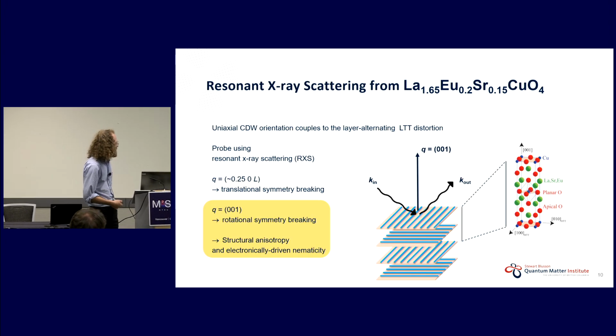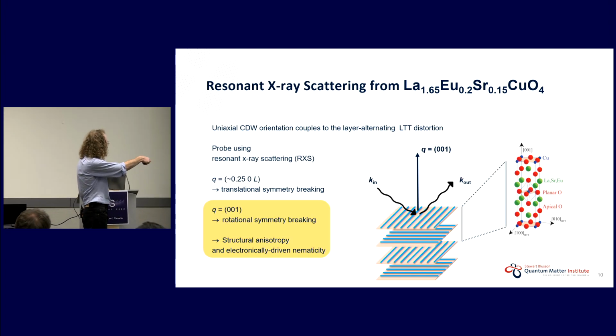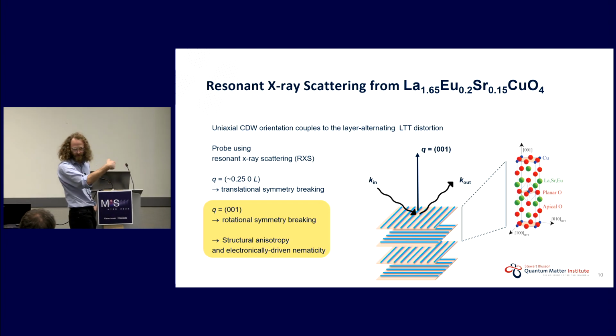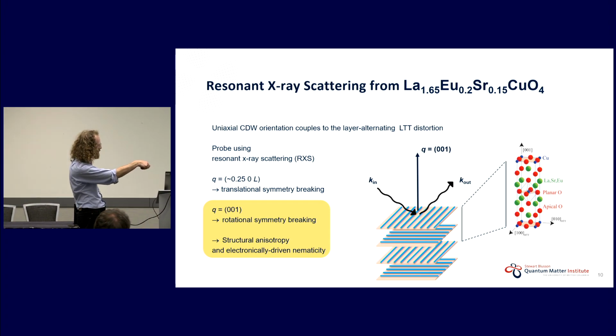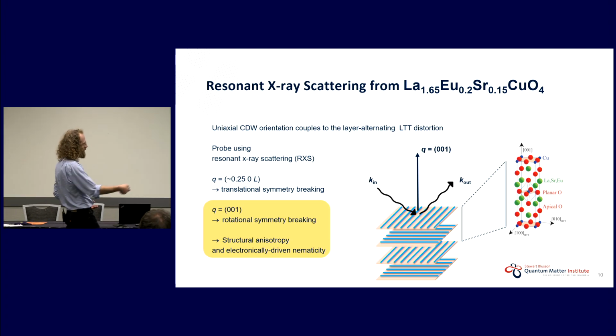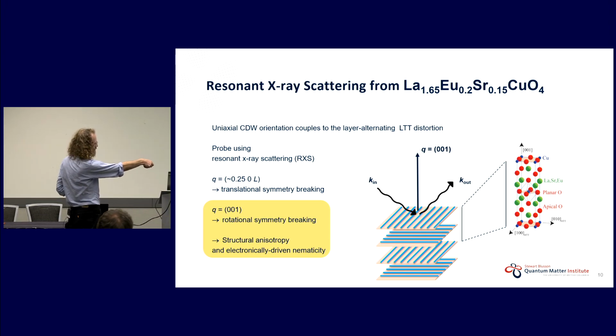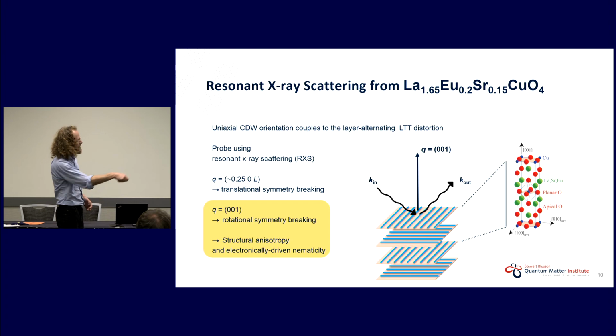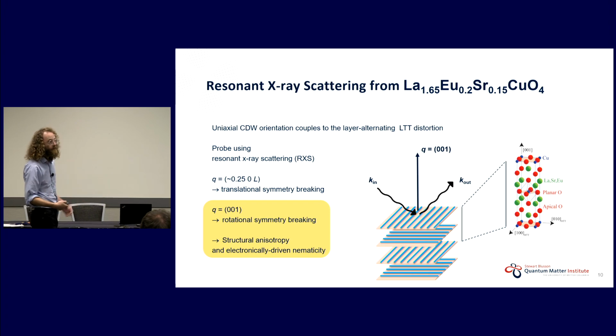So in diffraction, now we have two features we can look at. If we look at the in-plane momentum transfer, we can have finite in-plane momentum transfer showing us the translational symmetry breaking, or we can go to Q equals 0 in plane, where we're seeing essentially this rotational symmetry breaking, and we're able to see it because it's periodic in the L direction. So this doesn't have to be translational symmetry breaking in the plane. You can just have nematic character. As long as it's rotating 90 degrees each time, you'll get a Bragg peak there.